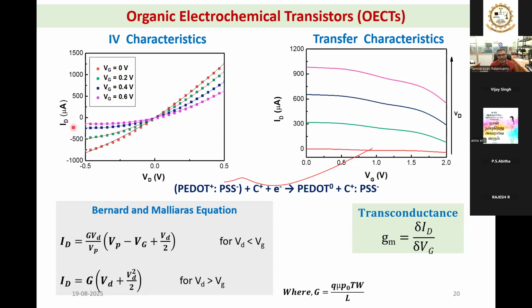Okay, so this is what we have seen in the literature, and we also achieved it. So from this we can understand that our transistor, our OECT, is working perfectly. On the other hand, the transfer characteristics tell you how much your electrode can affect the conductivity in your system. For instance, in case your gate has no effect on your channel conductance, if there is no transconductance at all, then you will have a very parallel straight line.